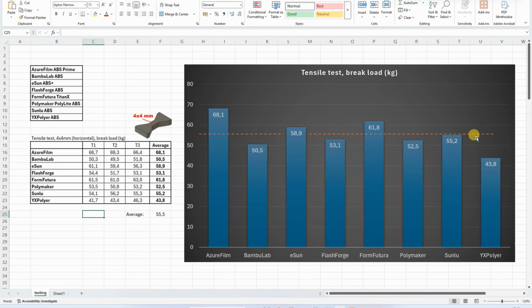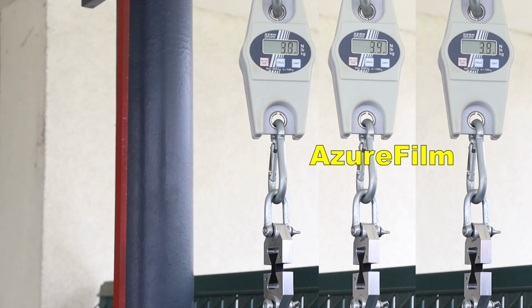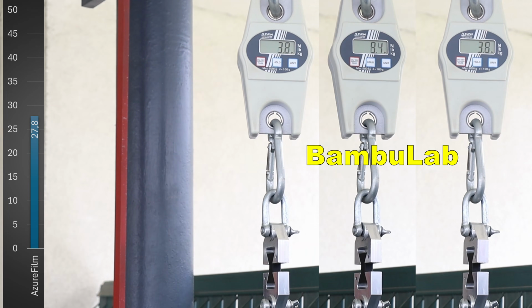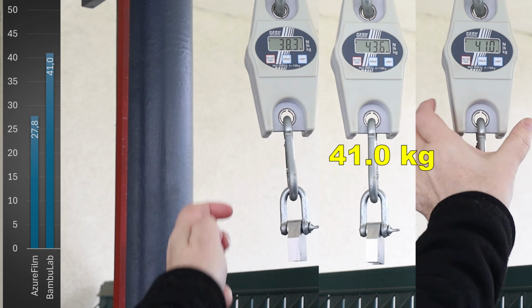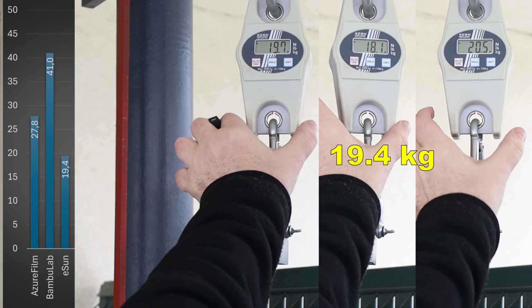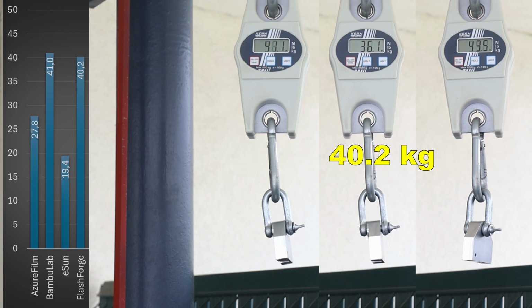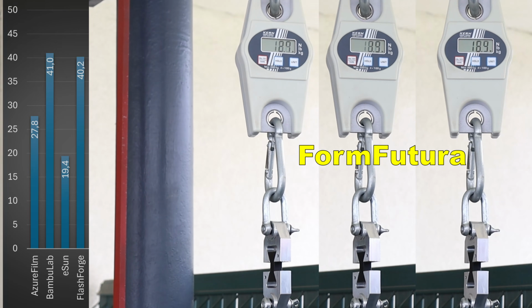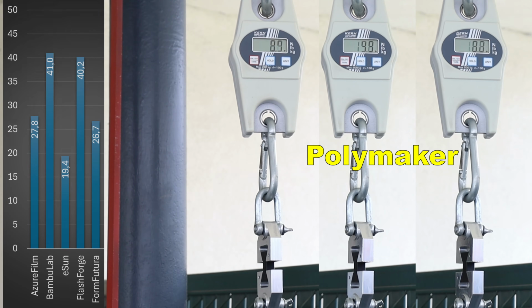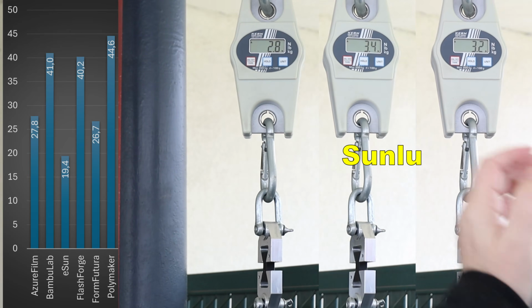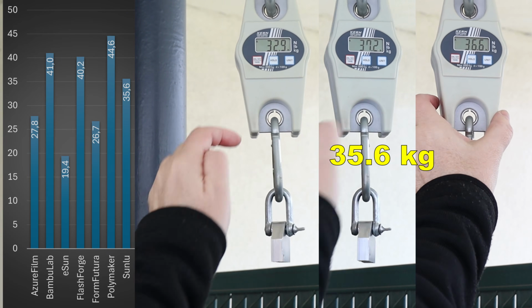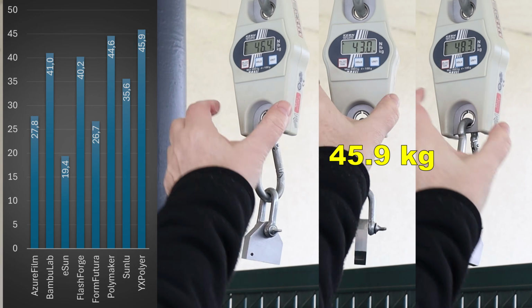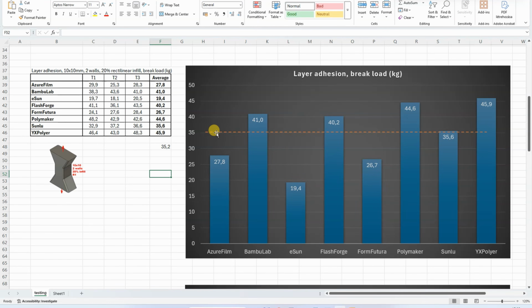Most of them are very close to the average line. The AzureFilm was the best and the YXPolyer was the weakest in this test. Layer adhesion test with vertically printed objects, 10 by 10 mm on smallest cross-section area, but printed with 2 walls and 20% rectilinear infill. This time we can see a bigger difference between these materials. This is the average line and the weakest now was the eSun, and 2 best are the Polymaker and YXPolyer.